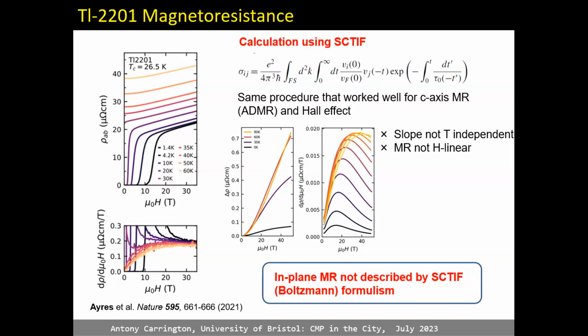So then the question, if you think about it for a minute, is why doesn't A short out B? That is not very clear. You can develop a model, which I don't really like very much, but just for the sake of argument, where you've got a kind of real space mixture of the two things. With an effective medium theory, where you've got conductor A, which has linear in T resistance and an H linear magnetoresistance, and then a Fermi liquid part, and you mix them together, then you can replicate what you get. Does that mean coupling them in series or parallel?